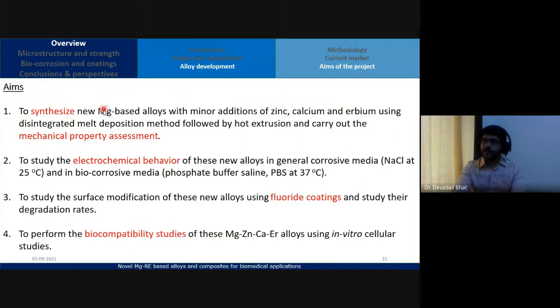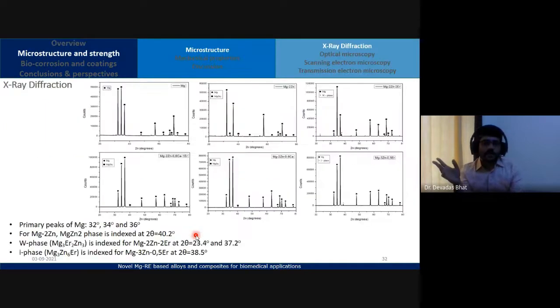In our project, what we aimed for is to develop new materials and study the electrochemical behavior. We have developed fluoride coatings, and we have performed some biocompatibility studies. Whenever we design a new material, of course, we cut it, make small samples, and polish it. The first thing that you do is microstructure, and in the microstructure, the first thing is X-ray diffraction. So perform X-ray diffraction and get the information on the different phases that are present. We index the peaks, and we get some information with respect to what the different phases are.